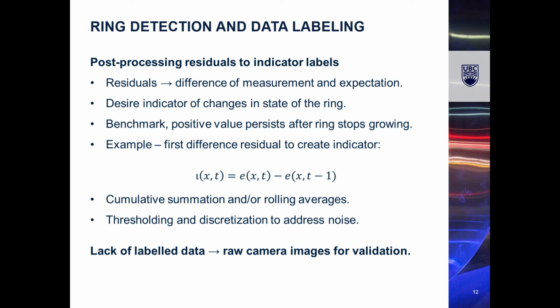Once the residuals are created, the next step is to post-process the residuals to develop the ring formation indicator. While the residual may continue to reflect a persistent mismatch between the estimated and measured shell temperature, this is not desirable for our indicator. Instead, we would like the indicator to reflect the changes in the state of the ring. Therefore, one simple example of post-processing is to take the first difference of the residual such that the temperature mismatch is reflected in the indicator only when it changes. Additional post-processing activities can involve rolling averages, thresholding, and discretization to address noise. Finally, it is important to carefully validate the ring indicator with the raw camera images.